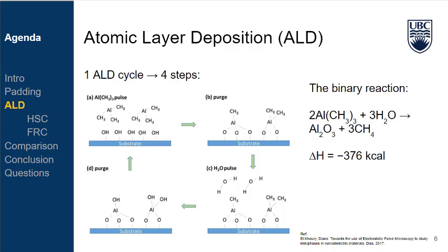As the precursor and co-reactant species are transported into the reactor separately, two surface reactions occur, and each of the surface reactions is self-limiting. Then, the two reactions proceed sequentially, eventually depositing an atomic level controlled film.